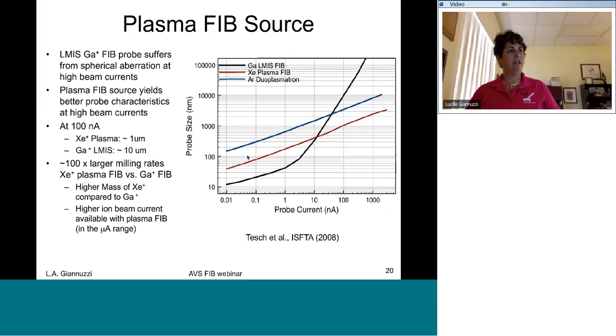So the current density at the high end is very good. And again, this is a similar graph to what I showed before. Probe size is a function of probe current. This is your gallium up here, where you see the knee. This extends upward because of spherical aberration issues. And at the high end, the xenon plasma FIB just continues to extend linearly on this log-log plot, so you get really, really good probe size, probe current behavior, allowing you to mill very large things very effectively.